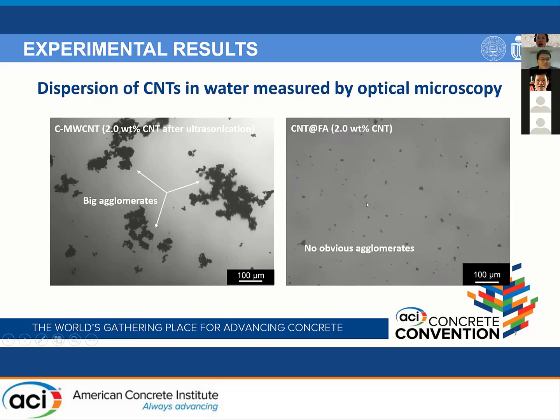And for the CNT@FA particles, the dispersion result is shown in the right figure. From this figure, we can see that no obvious agglomerates can be seen, and only dozens of small black stains that were uniformly dispersed in the suspension. This result confirmed that the synthesized CNT@FA particles had a better dispersion state compared with commercial carbon nanotubes, suggesting that CNT@FA had a better dispersibility in water.